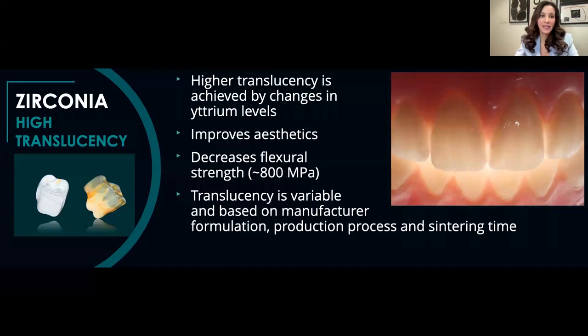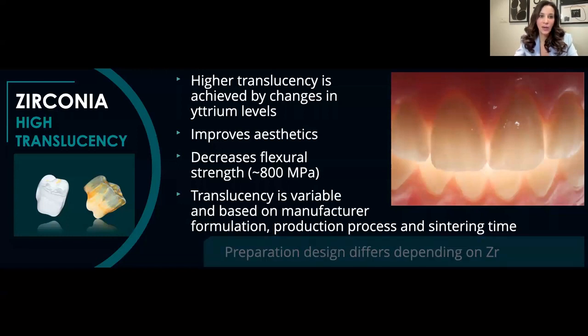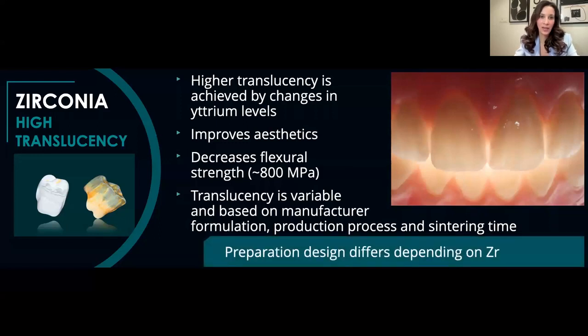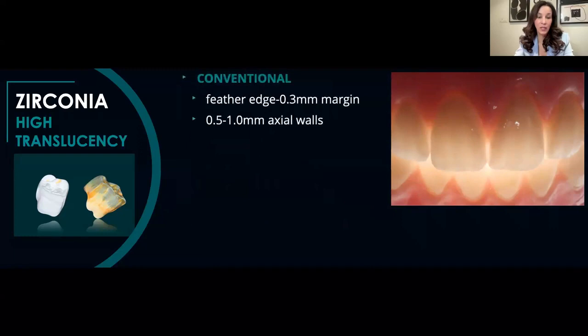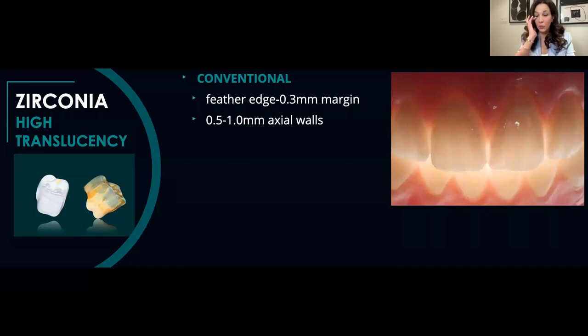And the key to this, and what I want you to really understand, is that your preparation design differs depending on your zirconia. So that's why I had this flashing. Understand that your preparation design will be different if you're planning to use a high translucency material versus a monolithic conventional zirconia. So for our conventional material, the 3Y-TZP, you can have feather edges or 0.3 millimeter margins. It could be a very minimally invasive, minimal reduction with feather edge margins. Your vertical prep margins are 0.3 millimeters, and your axial wall reduction could be as little as 0.5 millimeters to 1 millimeter. That's for your conventional zirconia.